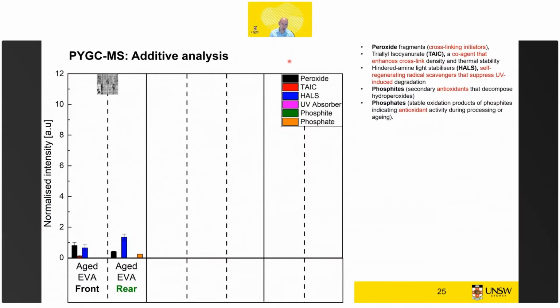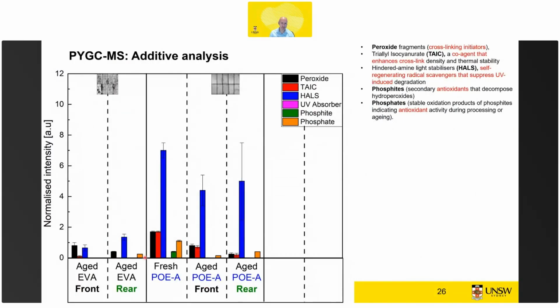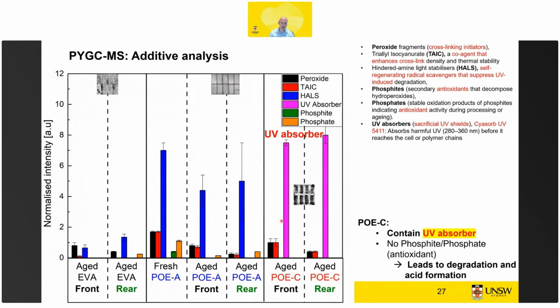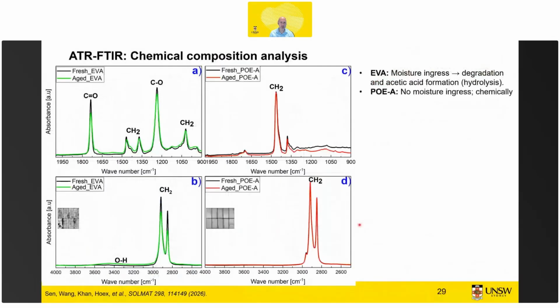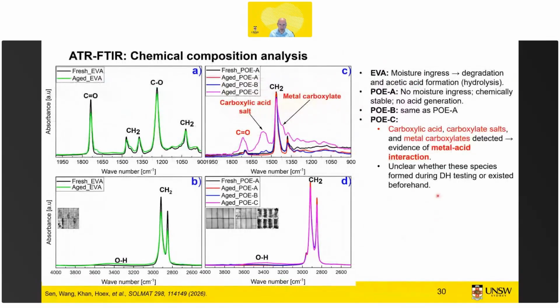So we tested for a number of them, and then we tested this Aged EVA, where we saw this acetic acid. But we saw that there were not really a lot more additives in there. Then POE-A, which had quite a good performance, we see a lot of HALS, which is a UV-induced degradation stabilizer, so for UV-induced degradation of the encapsulant, not of the cell. But clearly that was not interacting with the TOPCon cell. But then if we looked at the worst performing POE-C that had a certain type of UV absorber, and based on the comparative analysis, we identified that was the root cause of the strong degradation.